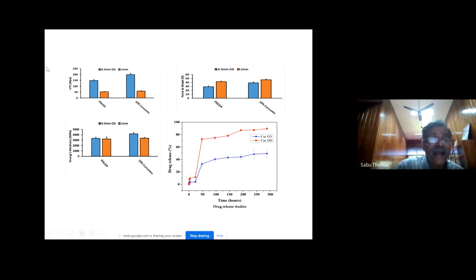If you look at the ultimate strength of this material, you will find that this is the neat copolymer. The 0.5 mm showed higher mechanical properties. And this is 1 mm. This is with 10% of curcumin. When you add 10% of curcumin, you see the mechanical strength goes up. So curcumin also has a reinforcing effect. And this is Young's modulus. Young's modulus also, you find the same thing. When you add a little bit of curcumin, you see the strength goes up.